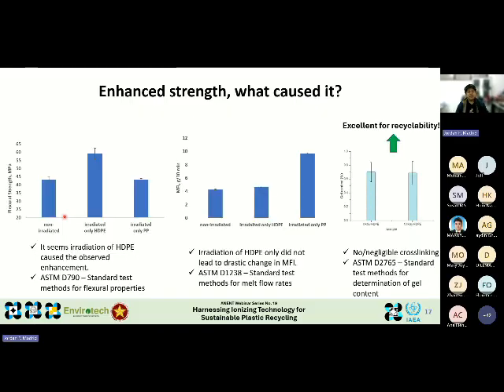And of course, as scientists, we cannot stop at simply observing enhancement in properties or observing stronger materials. We need to ask why. What is the reason behind the observed enhancement? What is the reason behind the trend? And so we examined the effect of irradiating the individual components, the high density polyethylene and the polypropylene, within the optimal blend that we've established in the laboratory.